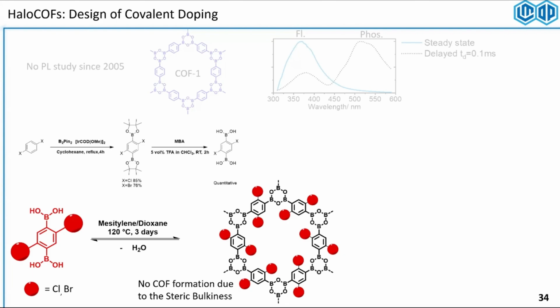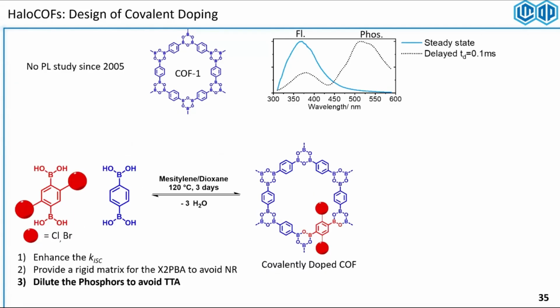Well, it didn't work with many trials, probably because of the steric hindrance of all these halogenated derivatives kind of cramping inside the cavity of the COF and not allowing the COF to form or have proper pi-pi stacks anymore. So I took a step back. I thought, we can make COF1. What if we dope it with some of these halogenated precursors? We can still form the COF. Presumably, it will stay crystalline, especially in low doping percentages. But we covalently dope this framework with these halogenated precursors, not only to enhance the intersystem crossing and provide a rigid matrix for these halogenated precursors to have less vibrational decay, but also we dilute them inside this framework so that the triplets cannot meet each other and annihilate each other anymore, right?